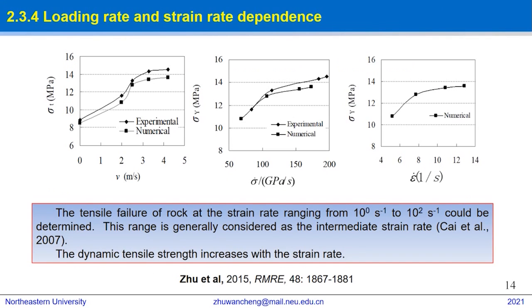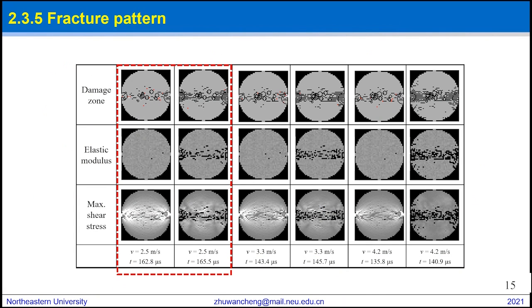This slide shows the loading rate and strain rate dependence. The tensile failure of rock at strain rates ranging from 1 to 100 per second could be measured. This range is generally considered as the intermediate strain rate, as defined by Cai et al. in 2007. The figure shows the rate dependency is found in the results of both experiments and numerical simulations, i.e., the dynamic tensile strength increases with the strain rate. The simulation results are shown in the figure.